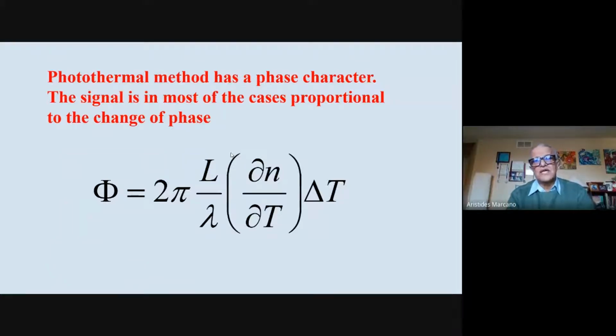So it gives you a factor of 10 to the minus 7, but you can actually recover that factor just by looking at the next number, which is the length of the sample divided by the wavelength. So the length of the sample could be a few centimeters, maybe millimeters, but still lambda is 500 nanometers. It's very small compared to that. So you can actually see that you can create changes in phase that are significant for our experiment. And that's a phase experiment, similar to interferometry. For a long time, people believed interferometry is the top of the experiments, the most sensitive experiments you can do. You know that it's being used for detection of gravitational waves, the idea of the interferometer of Michelson.